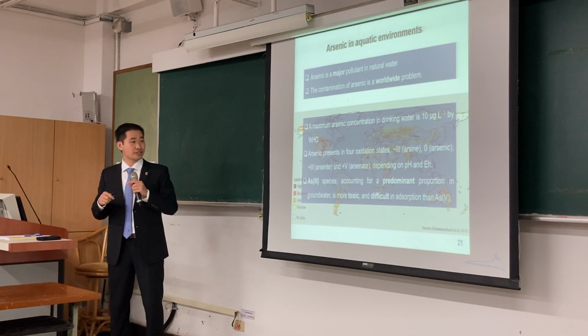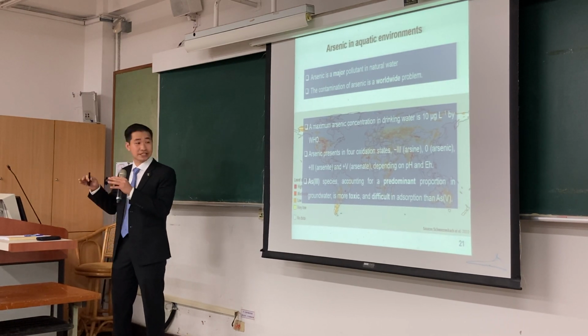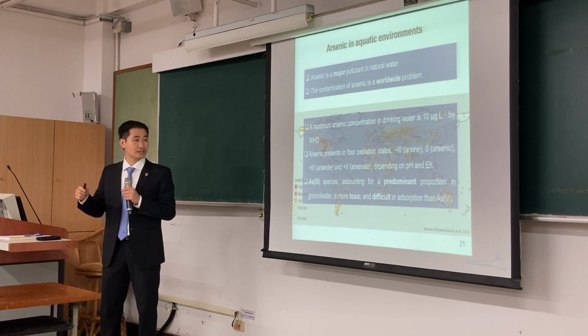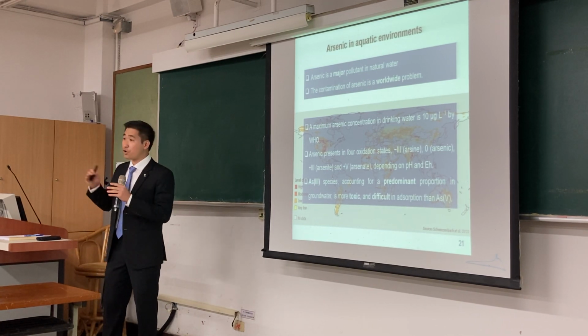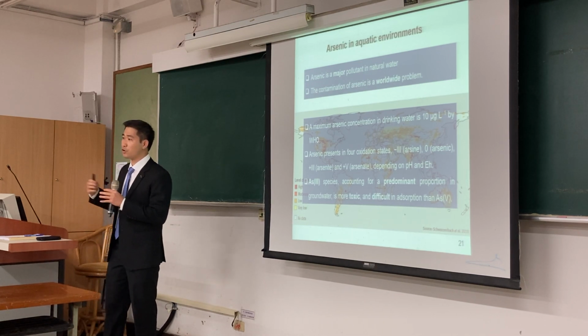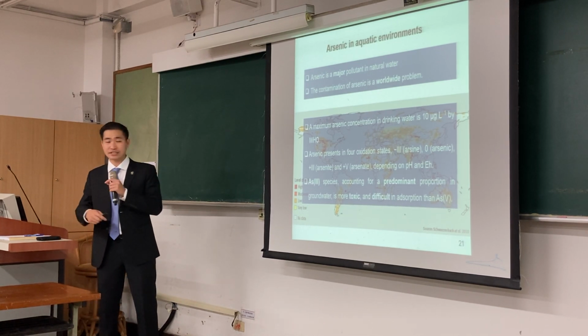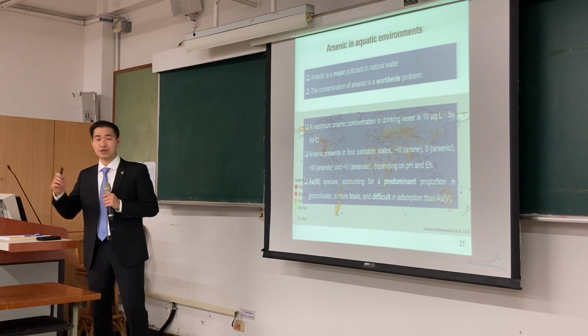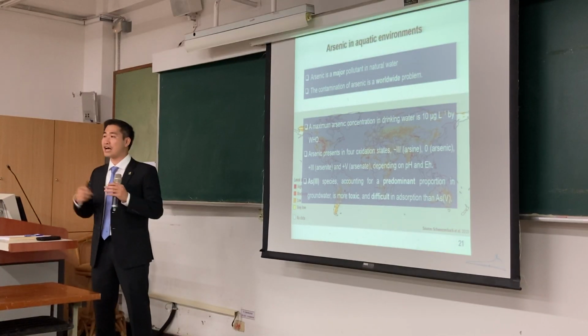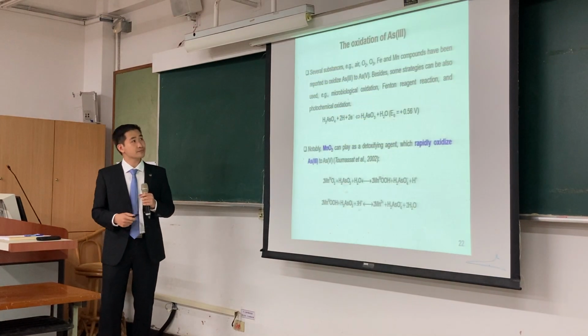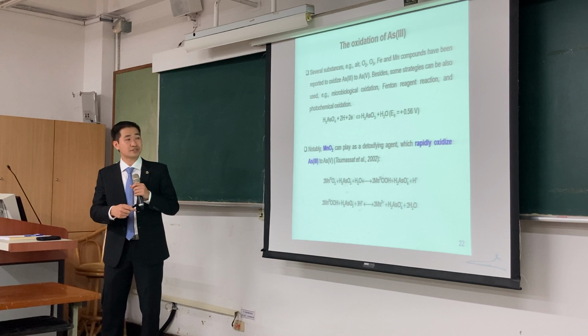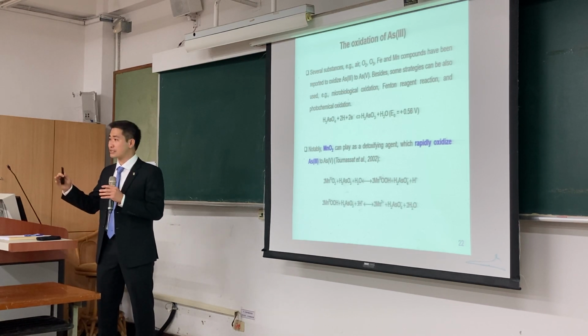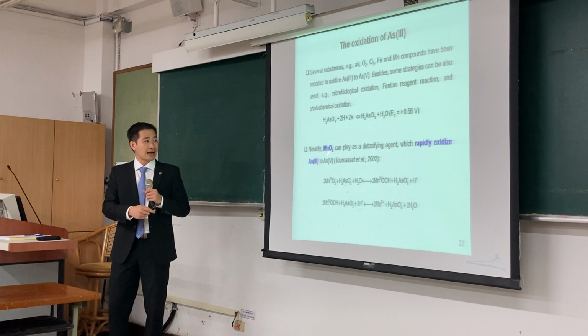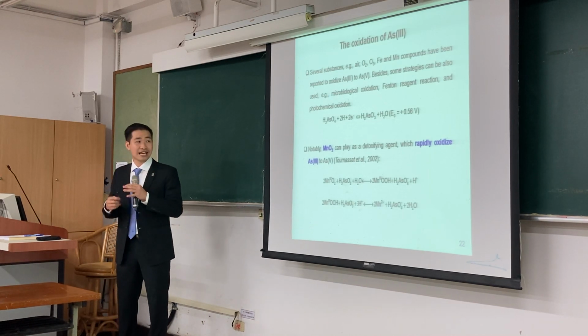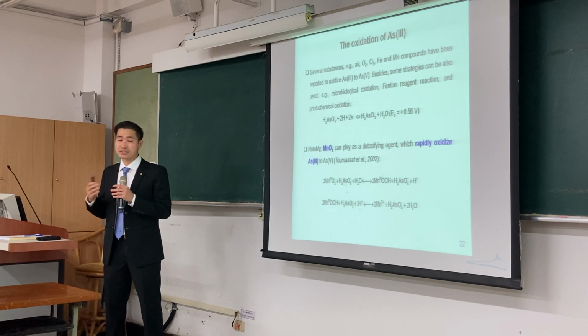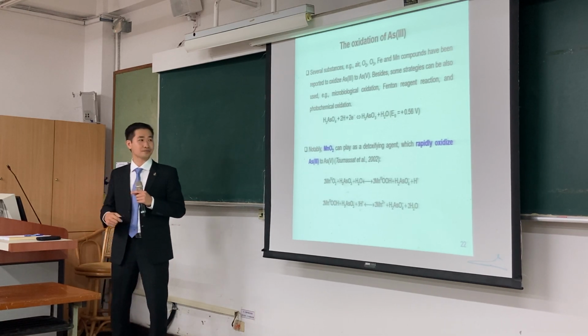Arsenic is present in 4 oxidation states, and especially arsenic-3 species account for the predominant portion in groundwater and are more toxic and difficult to remove compared to arsenic-5. So the solution here is to oxidize arsenic-3 to arsenic-5 to enhance arsenic-3 removal. Several substances and strategies can be applied to oxidize arsenic-3 to arsenic-5. Notably, manganese dioxide can rapidly oxidize arsenic-3 to arsenic-5.